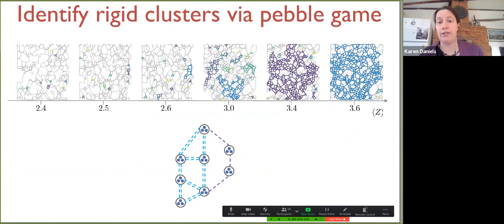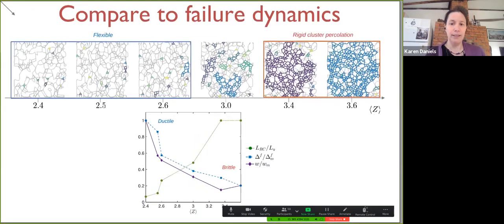What you're seeing here are those rigid clusters that we got from the pebble game. On the left, you can see that there's not many rigid clusters. They're small and they're sparse. As you go towards the right with higher connectivity, you have system spanning rigid clusters, and then in between, you have in between. As statistical physicists, this is not a surprise to us. So we can consider the ones on the left as being flexible. They're mostly composed of floppy regions. These are things where all those bars can bend and accommodate a tremendous amount of displacement. Everything on the right, where we have rigid cluster percolation, has very much fewer ways it can accommodate any strain that's imposed. So left is flexible, corresponds to ductile. Rigid cluster percolation corresponds to brittle. If it fails, it's probably going to cause a cascading failure.